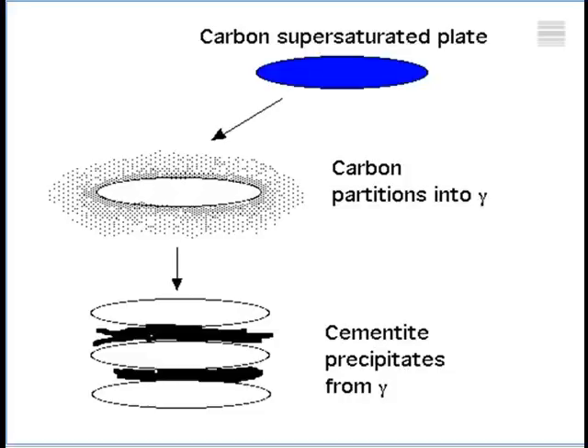Now this phase is not good. It's cementite, it's a brittle phase. And if you have a very strong steel, you know, we're talking about, say, 2,000 megapascals, then even cementite particles are not good. But fortunately, we can stop the reaction here. Okay? If we add silicon to our steel, then silicon stops the precipitation of cementite from austenite. So we are left with beautiful plates of bainitic ferrite and carbon-enriched retained austenite, and that austenite is extremely cheap to produce because you are using carbon. Okay, you're not using very expensive nickel and elements of that sort to stabilize the austenite.